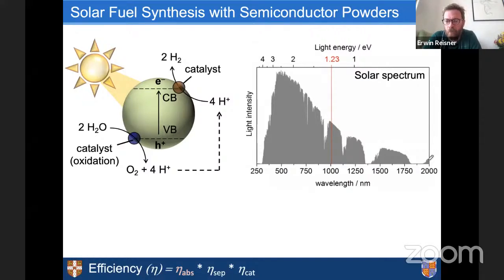If the band gap is too large, we lose a lot of the visible or the infrared region. If the band gap is very narrow, then we lose all of this high energy from the UV or blue light. So the best way is somewhere in the middle, and it always ends up being in the visible, which is the optimal region. That's why you always read in the publications about visible light responsive and visible light driven catalysis.